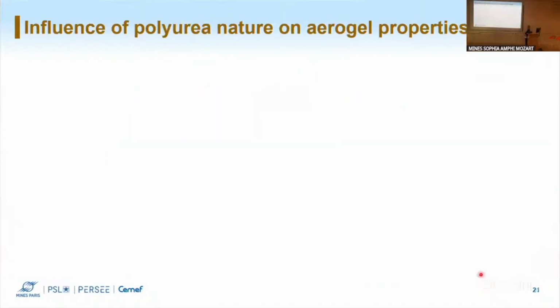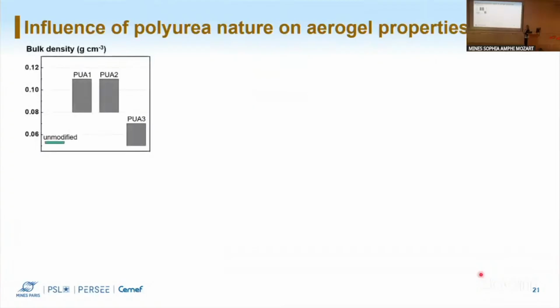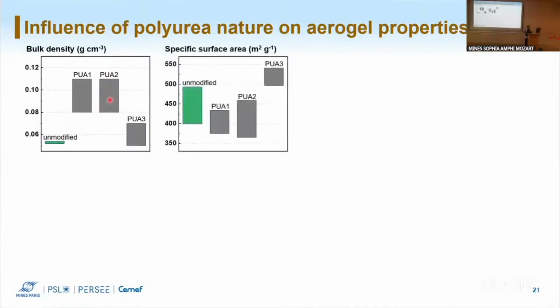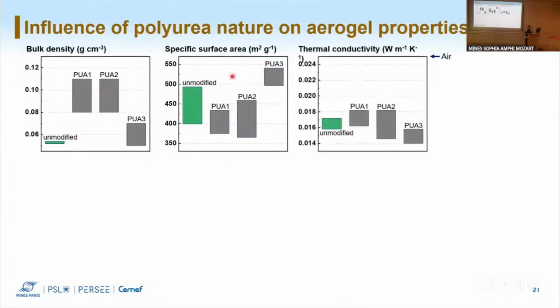Let's see first the influence of polyurea nature on our materials. We can see that the bulk density was low for all materials, but it was higher for the first and second type of polyurea used. Then the specific surface area decreased from the neat materials to the first and second type of polyurea. However, it stayed always at higher values for the third type of polyurea. The thermal conductivity was not really affected, so we see that the values are very close to the ones of the neat pectin aerogels, and we are satisfied with this.